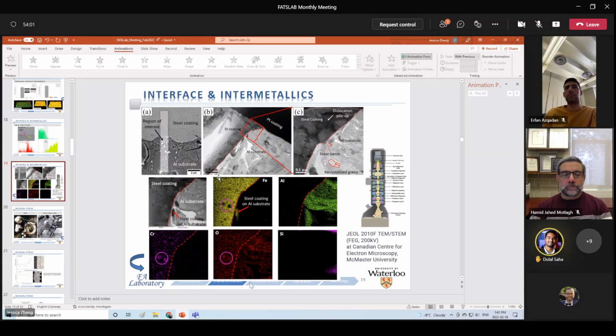which suggests that by mechanical interlocking alone we can obtain the strength we are getting from the pull test. And even if there is any intermediate layer present, it has a very minimal influence on the total strength of the coating. But obviously, we can say there will be a nano layer of intermetallic compound at the interface. Yeah.